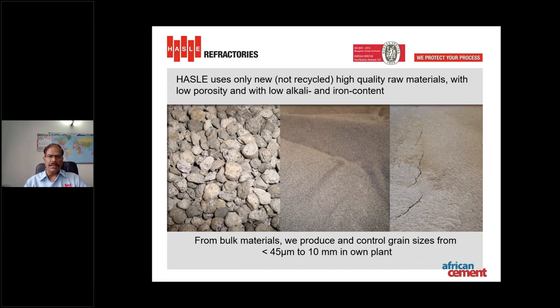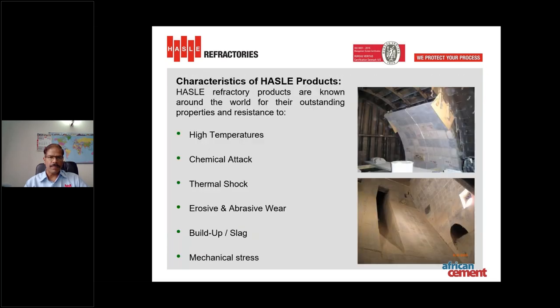HASLE always uses non-recycled, high quality raw materials with very low porosity and with low alkali and iron content. We never use recycled raw material for manufacturing our products. The major characteristics of HASLE products are outstanding properties and resistance to high temperature, chemical attack, thermal shock, erosive and abrasive wear, buildup, and mechanical stress, which are the main abuses in a cement plant.